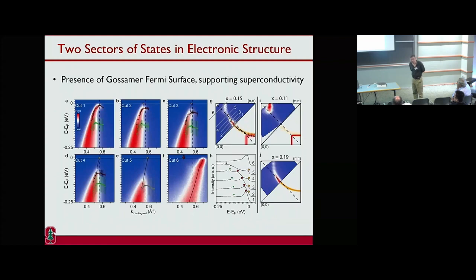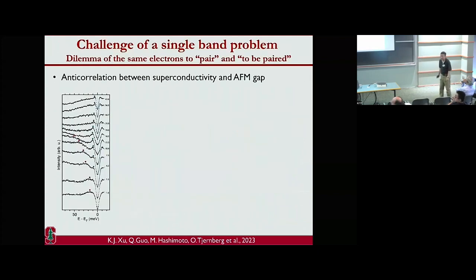This gap we can show is particle-hole asymmetric. And we believe this gap is a continuation of this antiferromagnetic gap. And the red blob there in square G is coming because of a finite integration window. Correct. Okay. You can have a d-wave superconductor if the node doesn't have a Fermi surface.